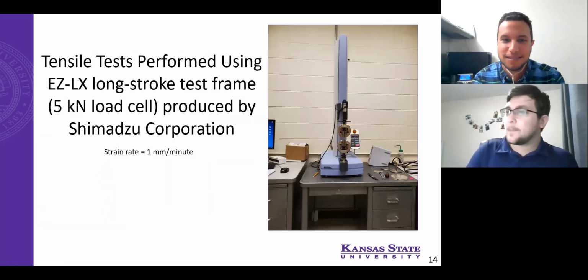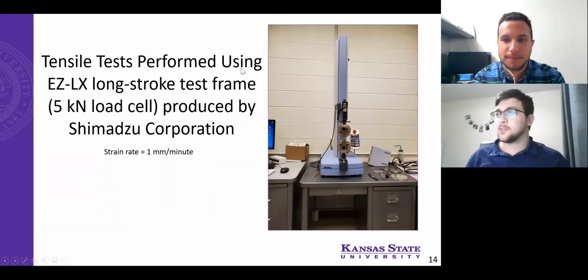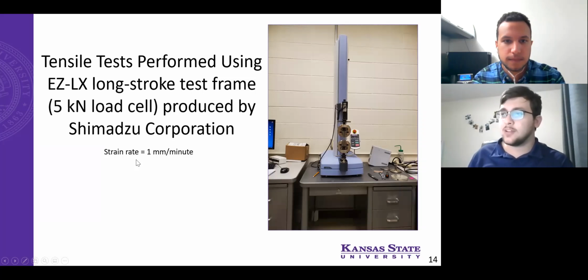Yeah, it's okay. So tensile tests were performed using the EZLX long stroke test frame with a 5 kilonewton load cell. We used a strain rate of 1 millimeter per minute. And this is just our setup at K-State.